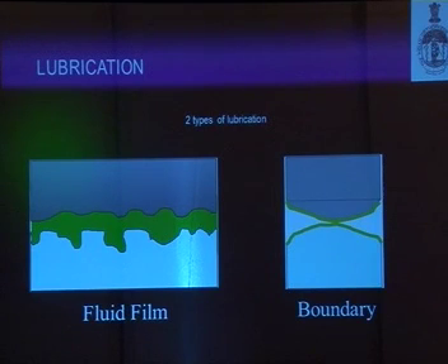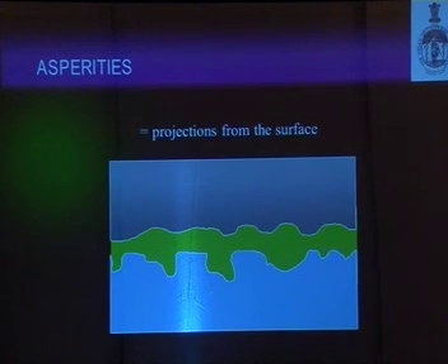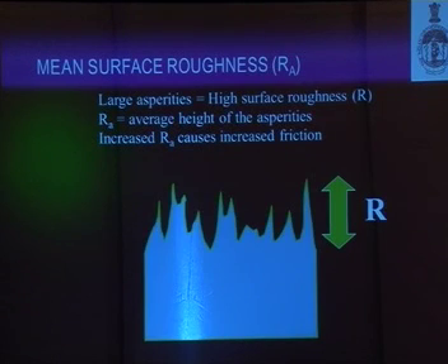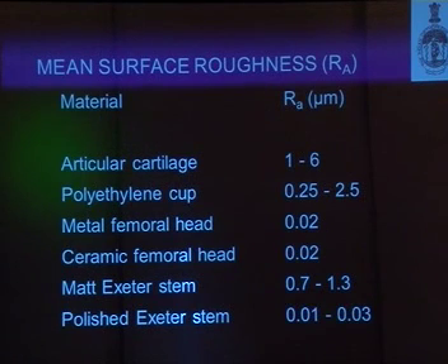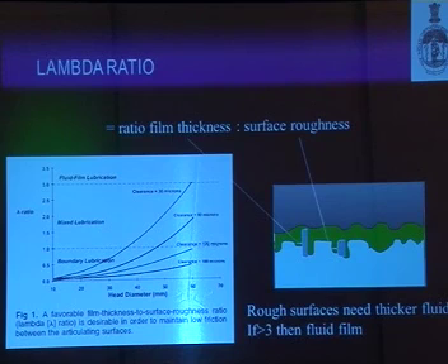So what's lubrication? Well, there are two types of lubrication, the fluid film or the boundary between the two articular surfaces. We have asperities at the joint surface, which are projections from the surface, both in the native cartilage or in the metal or polyethylene. And the surface roughness is more with high asperities, which are larger. The mean surface roughness is described for various different articulating surfaces. For polyethylene, it's 0.25 to 2.5, whereas for a ceramic femoral head, it's 0.02, which is the least. This brings us to the concept of lambda ratio, which is the ratio of film thickness to surface roughness.